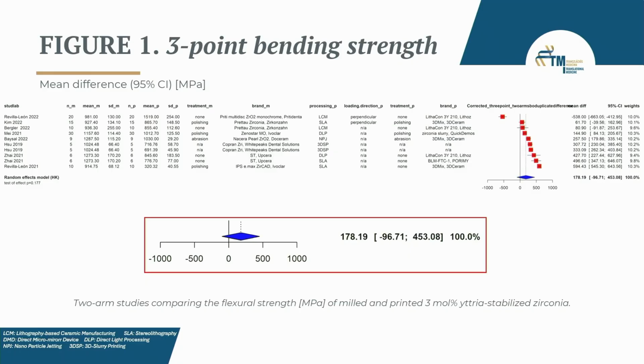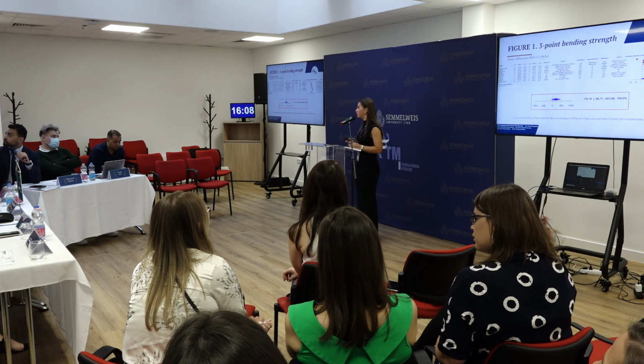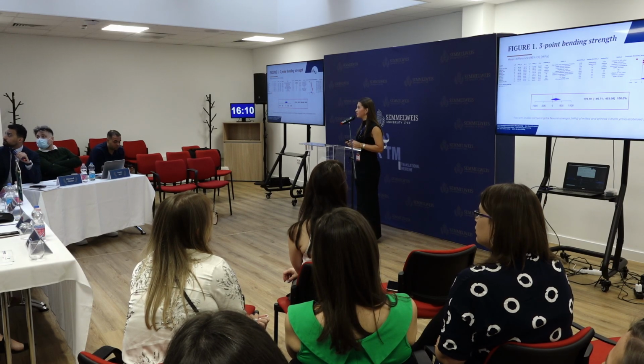Yes. What is interesting is that in this study we don't have information about the printing orientation. You can see the loading direction column. This means that the material was loaded perpendicularly to the printing direction, which gives us the best value. But in the third article, we don't have information about that. So maybe the printing orientation was different, and this is why this material didn't withstand forces.